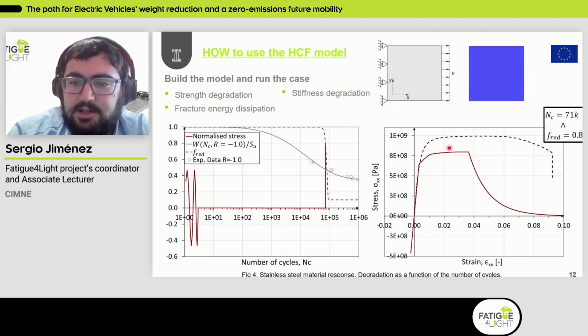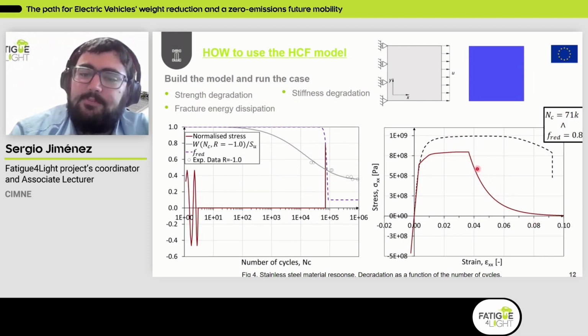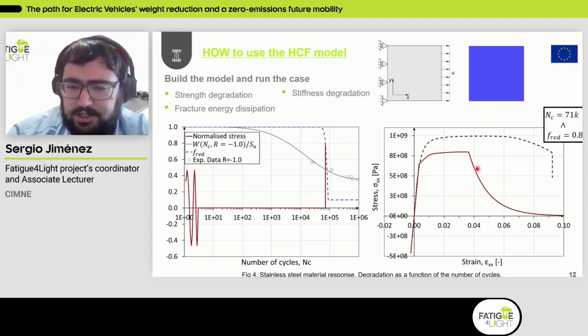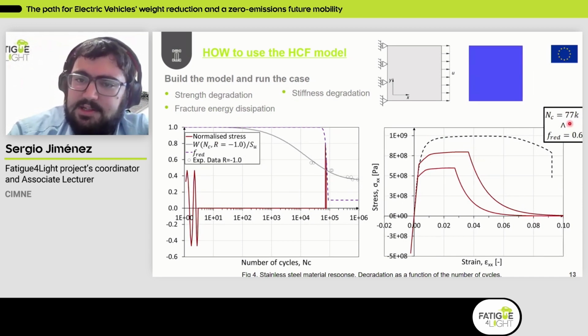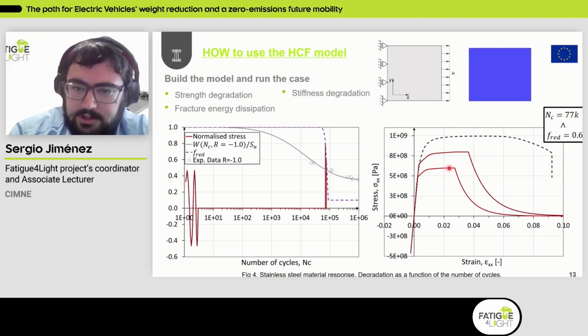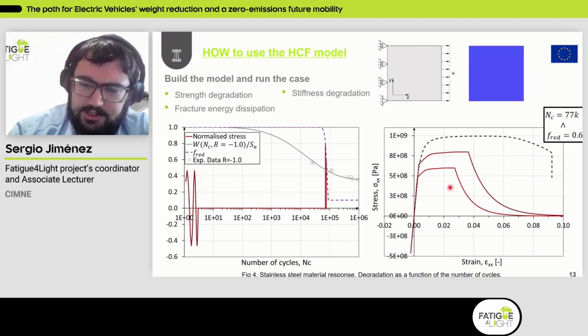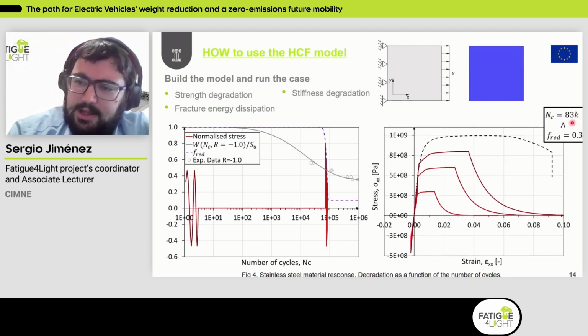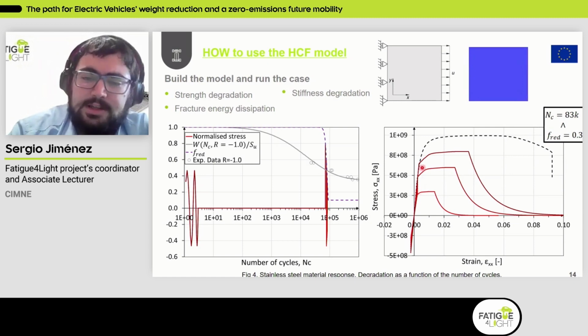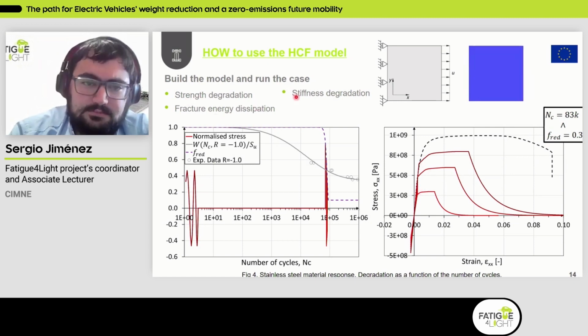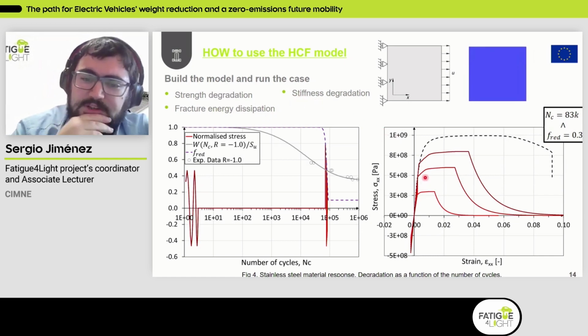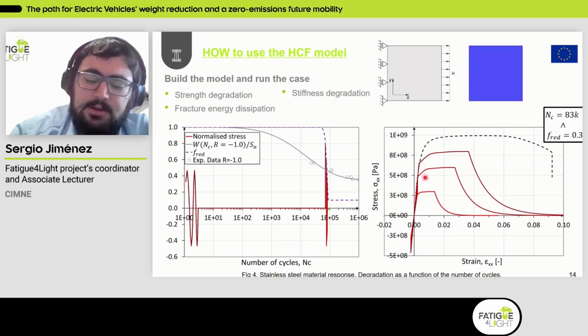So basically what happens in this material is that we have reduced the strength, and we also reduce the fracture energy of the material. If we perform exactly the same type of simulation, but now having this monotonic load after 77,000 cycles, what you can see is that the strength continues decreasing, and also the fracture energy. And then if we apply 83,000 cycles, what has happened is that the damage, the third inelastic region, has started. So together with the strength and the fracture energy dissipation, we also have a stiffness degradation computed based on this damage variable D that I was presenting previously.